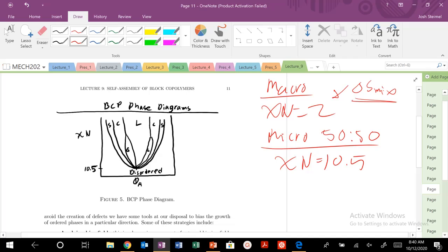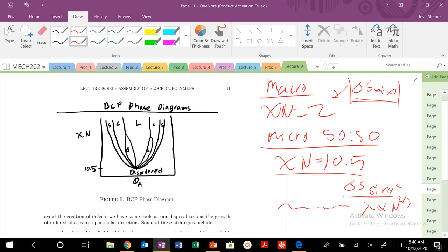We know that this contribution, the magnitude here, is usually pretty small for polymers, and for block copolymers, obviously, it would be small as well. So what really causes this more than fivefold increase in our critical chi-n value was not only this delta S of mixing, but the delta S of stretching term. In order to microphase separate into that lamella, those chains had to be stretched, and they stretched proportionally to n to the 2/3. Very stretched, even compared to a good solvent. So that stretching term is what caused us to need even higher chi-n values, lower temperatures, in order to microphase separate.